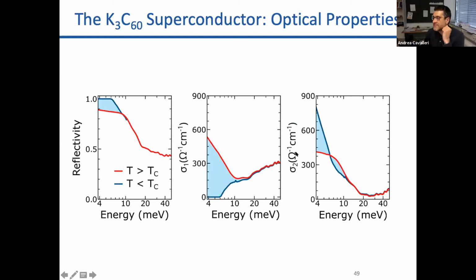And also in the imaginary part of the conductivity, one sees a divergent imaginary conductivity, which reflects the presence of a pole at 0 frequency in the real part. If this was a semiconductor, I would have a gap, but I wouldn't have this divergent sigma 2. What this divergent sigma 2 tells me is that there is condensation going on at low frequencies.